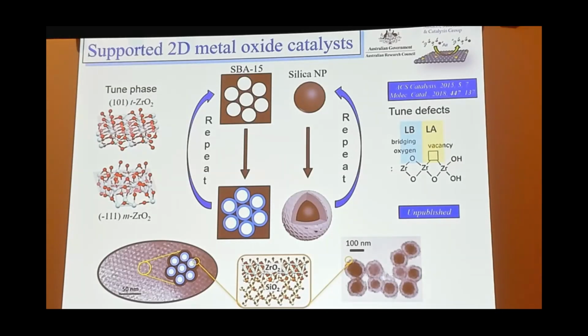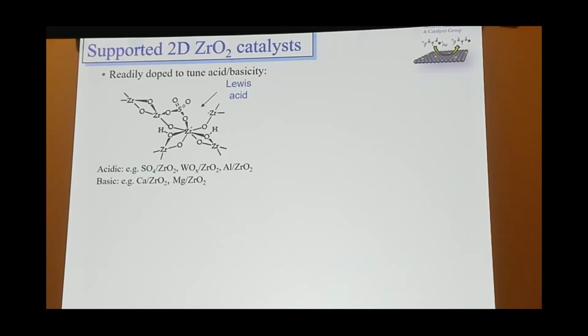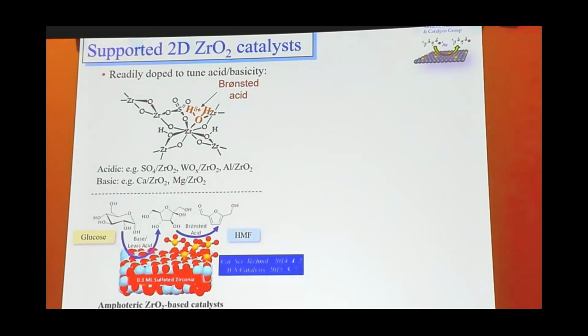So we've been looking at how you can grow zirconia films onto these scaffolds and then how we can tune their acid-base properties. And that's what I'm talking about for a pure zirconia sample. Of course, zirconia as well, you can dope it. So if you dope, for example, with sulfate groups, you can introduce strong acidity, and when that sample gets hydrated, it would be strong Brønsted acid. And there's various other dopants you can look at to introduce acidity or basicity into zirconia. So again, it's quite a versatile material.